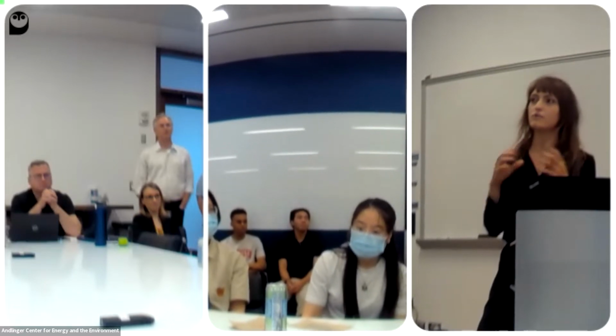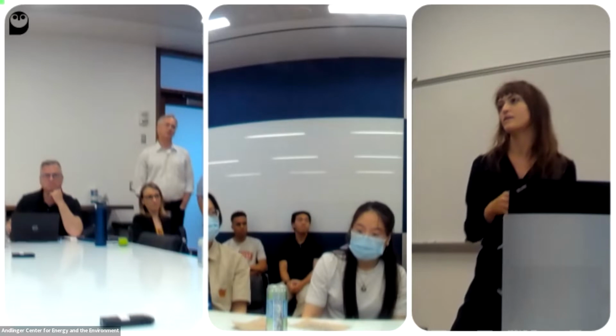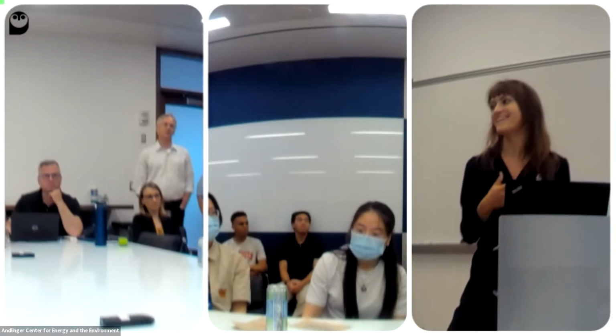Brush density is tricky. You can cleave your brushes off, concentrate them, and put them through a GPC to measure the molecular weight. Sneha can tell you a lot more about that than me, but it's challenging to do. So we're interested in an AFM-based technique, where we try to measure the swollen thickness. You can then relate the brush thickness in a good solvent, where it wants to extend, to the dry brush thickness and the density, because a less dense brush will swell more. That's something we're working on now, but it's a tricky problem.